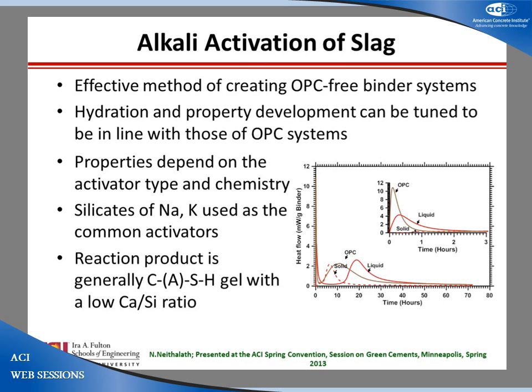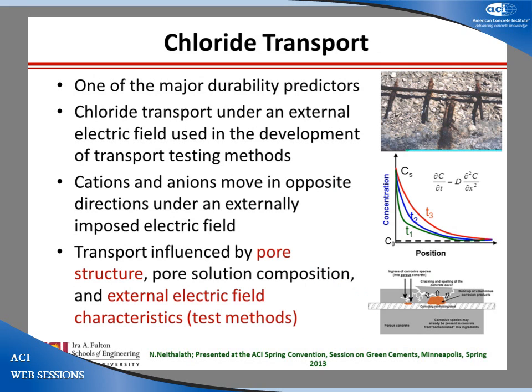The idea is, we talked in the morning about the activator type and chemistry influencing the process. Typically, sodium and potassium silicates are used. The reaction product is a calcium aluminosilicate gel with a low calcium to silica ratio, with sodium and potassium incorporated in the system. So that's the basic idea. But what we are trying to look at is how does the long-term microstructure of this material change, and how does that in turn affect the chloride transport.